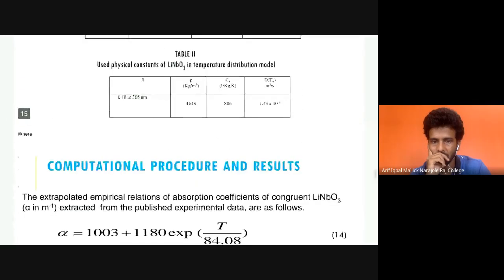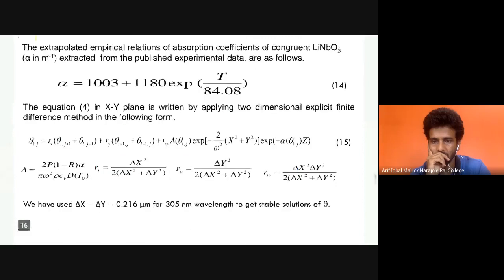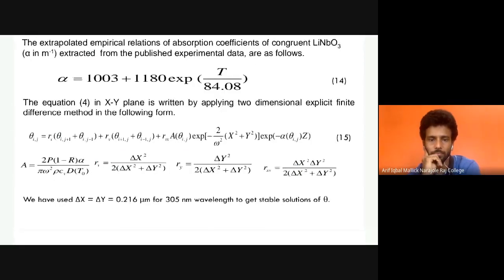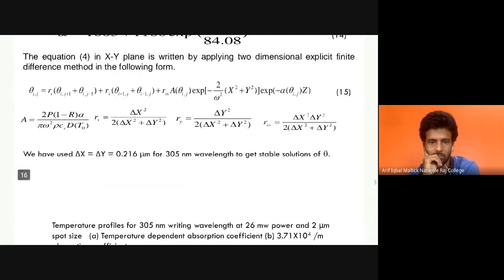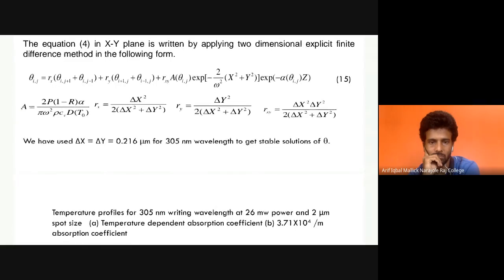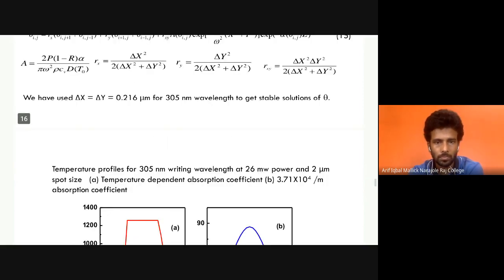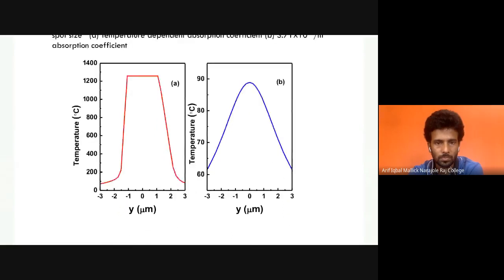For the computation procedure, from experimental published data, we fitted the equation and obtained a relation for the absorption coefficient which depends on temperature, written in equation 14. At first we obtain the temperature profile. We use the finite difference technique explicitly, with equation 15. We obtain the temperature profile, and then using the diffusion equation with the finite difference technique, we obtain the refractive index profile.